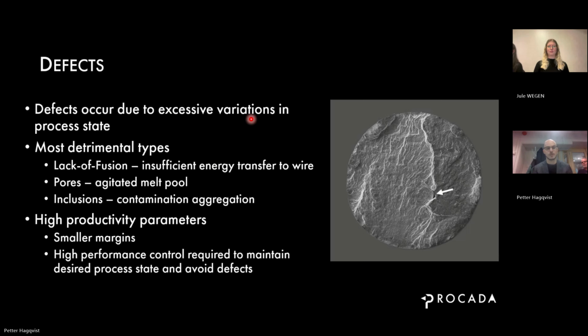There are also pores, which come from an agitated melt pool. So basically, if the melt pool is not flowing nicely, evenly, if it's got waves going back and forth, and if we've got crashing waves, we might capture a part of the surrounding atmosphere and it might get enclosed and solidified in the melt pool. And then that gives rise to a pore. We might also have inclusions, which typically come from some kind of contamination. It could be something in the atmosphere, but it could also be introduced through the feedstock material. So in this project, we are targeting high productivity parameters.